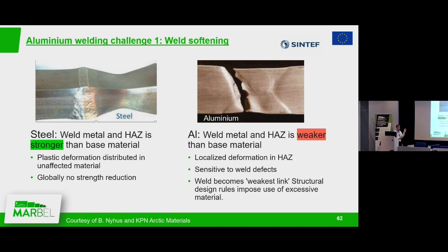we all know that if you weld something in steel, which is the otherwise required material in most car structures and components, it is not very difficult to create a weld and surrounding area that is stronger than the base material, the unaffected zone. So you use a weld material and the surrounding is stronger. If you have a deformation in operation and use, the deformation is distributed in the unaffected material, so you don't have to consider the weld as a weak zone.